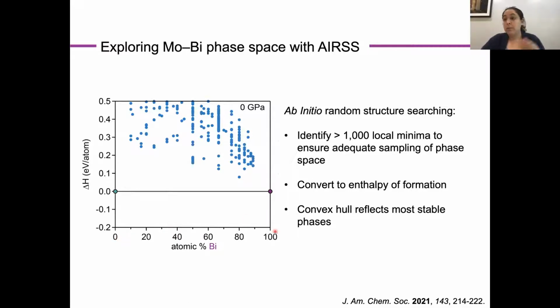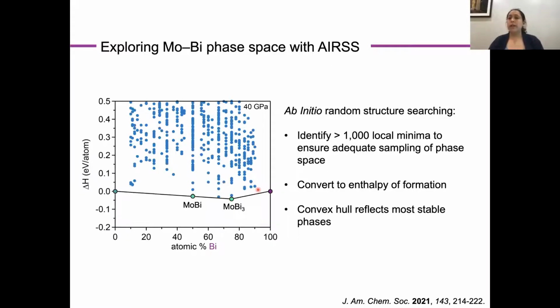To figure out what is the most stable structure in the system, I construct a convex hull, which is a line segment that encompasses all the data. And because of how high in energy all these blue dots are, all these molybdenum bismuth systems are relative to the elements themselves, I only need a line segment connecting molybdenum and bismuth, suggesting that they are the only stable materials in this phase space. And of course, that's exactly what we would expect given that empty phase diagram I showed you on a previous slide. Fortunately, though, by the time we get to 40 GPa, the situation has changed dramatically.